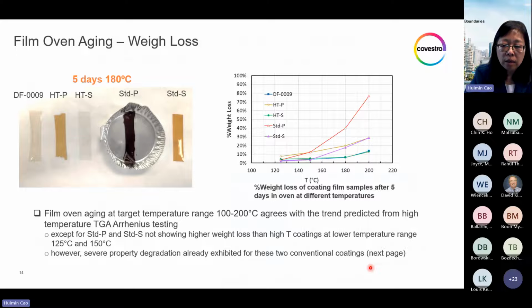Another traditional test is the oven testing. After 5 days of 180 degrees C oven aging, the standard primary turned completely dark. And it is a char-like material, which is probably only carbon left. There's no integrity at all of this coating after 5 days of 180 degrees C. It cannot peel from the aluminum pan as a film anymore. It just chips off. And the HTP is still a very nice film, only with some degree of yellowing.